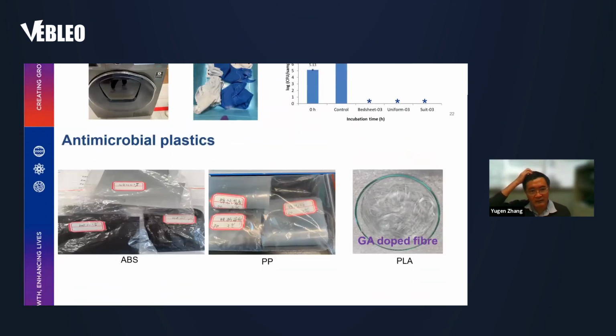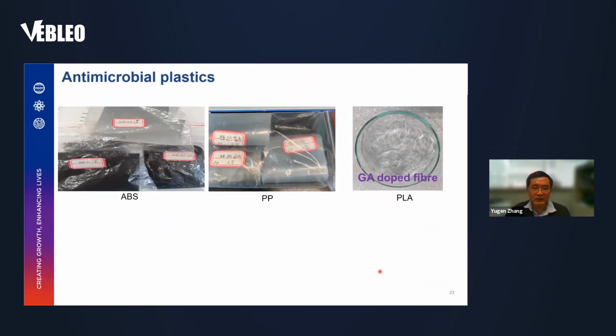In addition, our materials can also be used to make antimicrobial plastics. Basically you just use this as an ingredient, and during the molding process, you add it to the plastics, then the plastic will have these properties. For example, for this ABS, the polypropylene, and even for this PLA fiber. After incorporation of our materials, all these plastics demonstrate good antimicrobial properties.